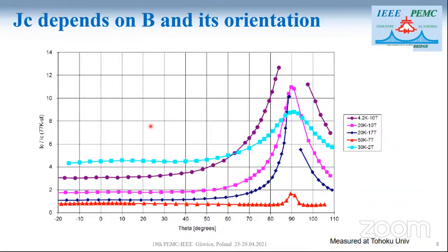Another essential feature for application design is the dependence of the current transport properties on the magnetic field and the angle at which it is applied to the face of the superconducting tape. We see on this curve tests conducted at Tohoku University. We also see the dependence on temperature, and you can see that if we decrease the temperature, you increase the performance. This is the ratio between the current density at a given temperature and the current density at 77 K. And you can see the angle of the magnetic field applied on the superconducting tape.